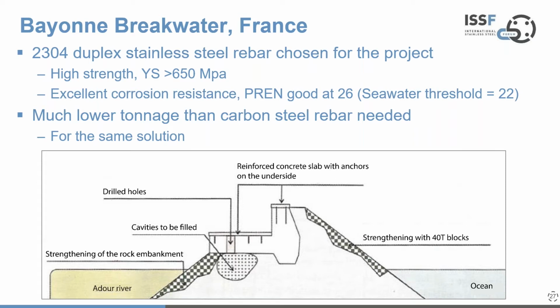So with this solution, we had a material that could not corrode in the environment, but also because of its high yield strength, it meant that a much lower tonnage of stainless steel was needed compared to carbon steel if that had been chosen again. And the original solution was with carbon steel. So there was good reason for choosing a stainless steel here. It ultimately led to a very sustainable solution.